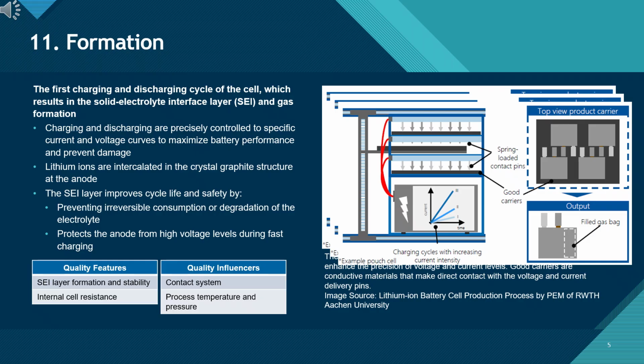The charging and discharging currents follow precisely defined voltage and current profiles. The equipment uses spring-loaded contact pins, shown in the diagram, to ensure consistent electrical contact with the terminals. Good carriers beneath the cells provide stable, conductive support, minimizing resistance variation from unit to unit. The formation environment, temperature, pressure, and contact quality directly affect SEI stability and internal resistance. As the SEI forms, small amounts of gas are generated, which is why you see the filled gas bag in the output image. Properly controlled formation results in a uniform SEI layer, lower internal resistance, and improved cycle life.